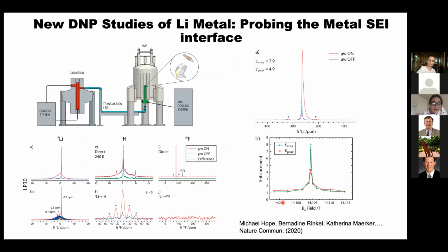I want to show you something else, which is really cool. And this is some new methods that we've been, I wouldn't say pioneering, for the reasons I'll explain in a second. We're using a technique called dynamic nuclear polarization, or DNP, where we transfer magnetization from the electron spins. And this technique was first invented back in the 50s and 60s. And it was predicted by Overhauser that you could actually use lithium metal DNP.